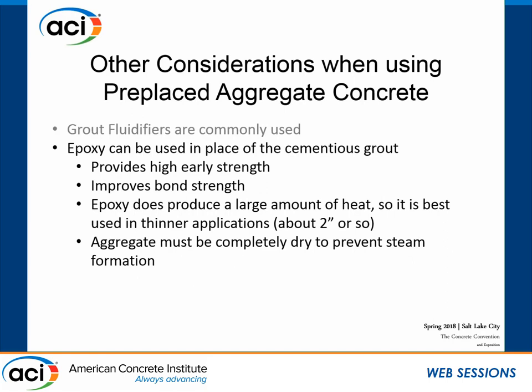Another interesting application is using epoxy instead of cementitious grout. This provides really great early strength and improves bond strength, but it is highly exothermic, so you'll get a lot of heat. About two inches or so is about as thick as you want to go with epoxy applications. Also, you would not pre-saturate the aggregate for epoxy because you can actually generate so much heat that you create steam.